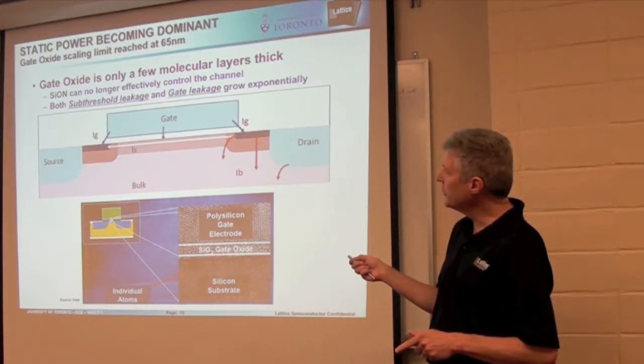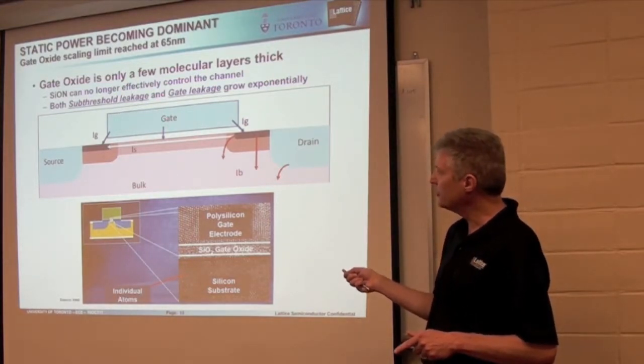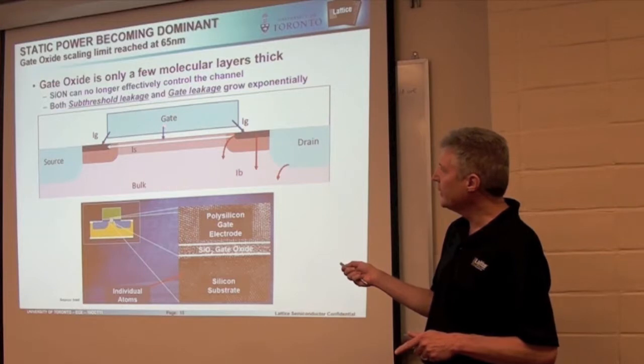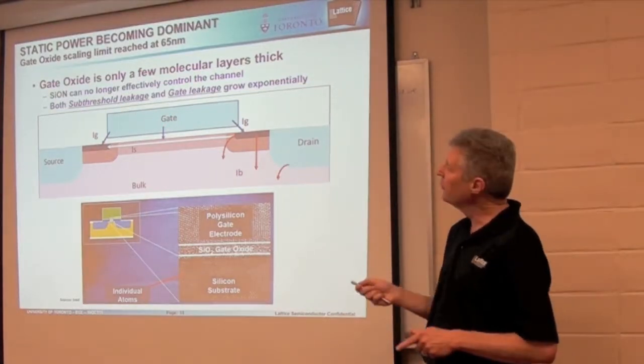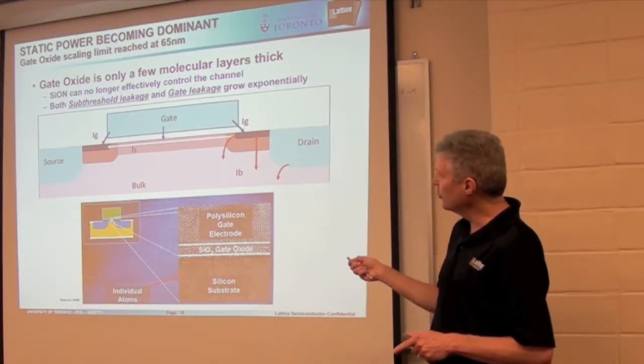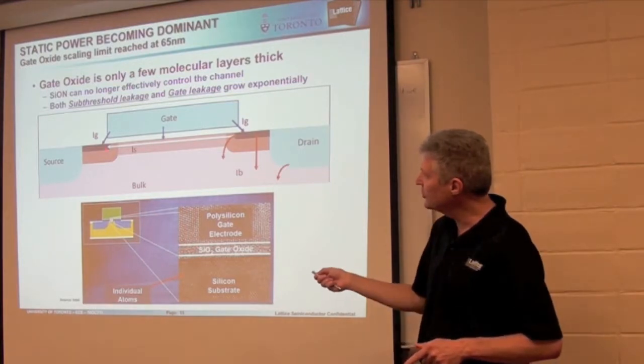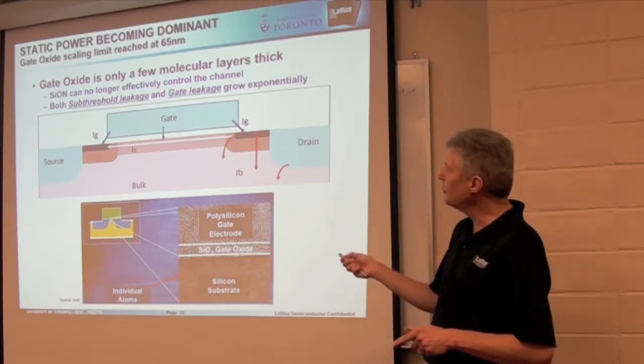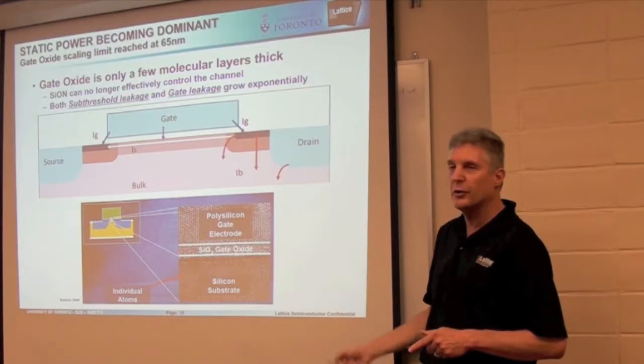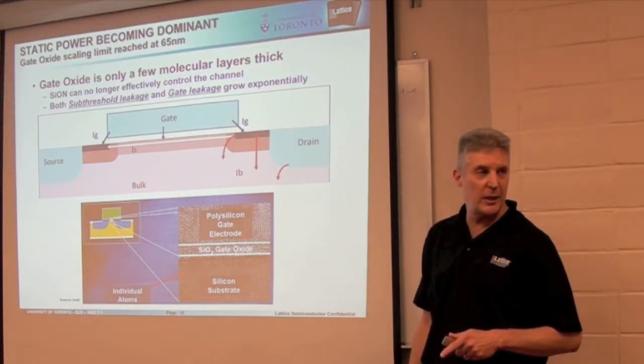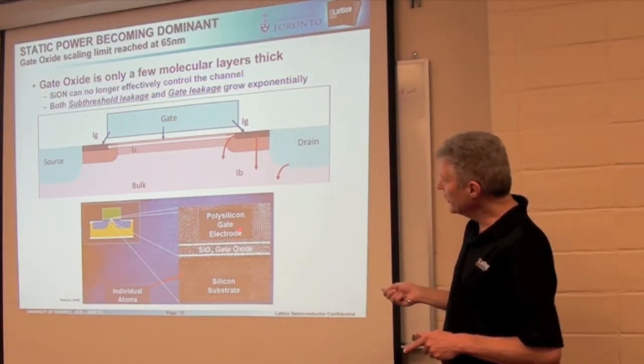The other source of leakage current is gate leakage, and that's leakage directly from the gate into the substrate through the gate oxide, and that's because of the thin gate oxide. So we have to thin the gate so that we can control this subthreshold leakage here and control the channel, but as we thin the gate, then we start to punch through the gate itself into the channel. And so this is an actual